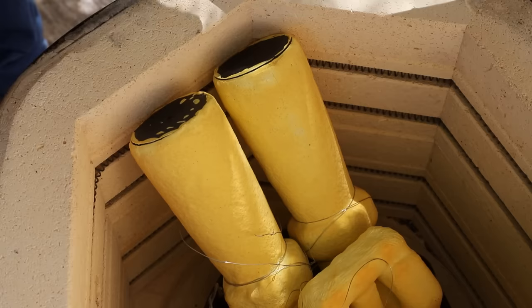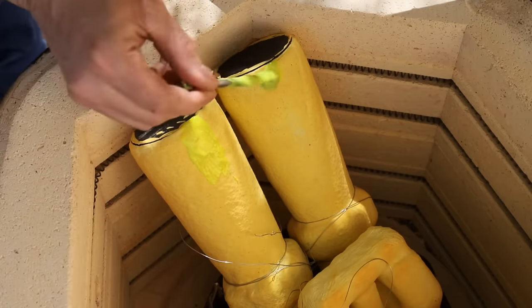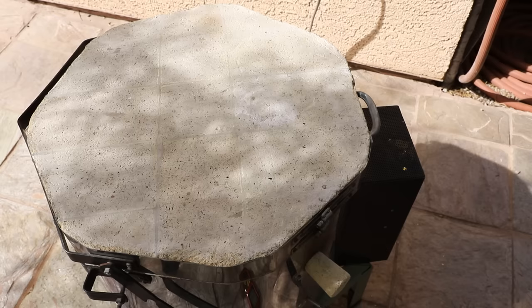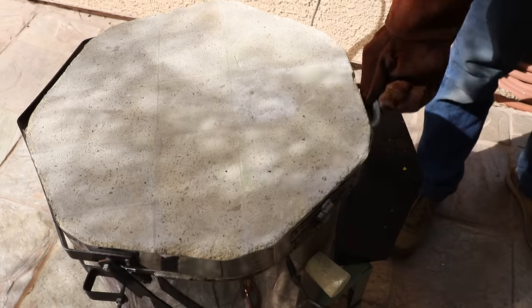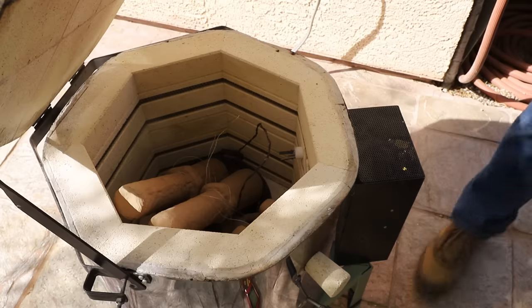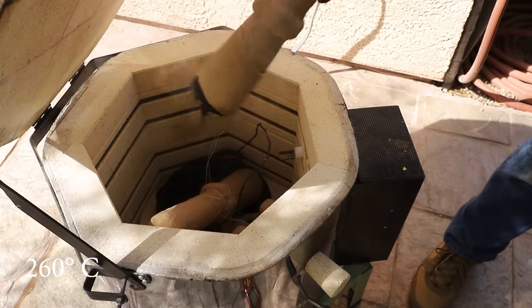I've figured out that a great way to seal the cracks is to brush on some slurry while the shells are still relatively hot. This way, the slurry dries almost instantly, allowing me to quickly build up thick patches. Once the cracks were fixed, I placed the shells back into the kiln and heated them up to about 500 degrees Fahrenheit, which is the temperature at which the PLA starts to melt out of the shells.